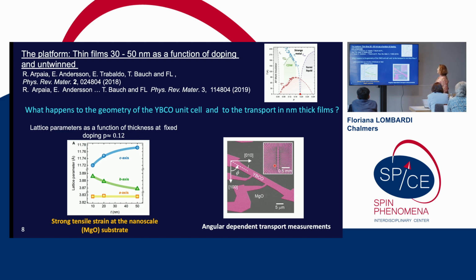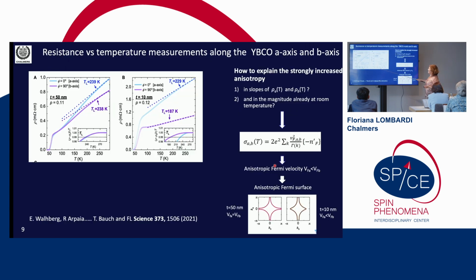Then you take these films and you make an angular dependence. So you can pattern Hall bars or nanowires as a function of the angle. And you see how the properties are changed. And this is quite surprising. This is at underdoped films, where you have depression of the superconductivity because there is competition with charge density wave. And you see the resistive transition along A and B, and they look pretty much the same because the chains are quite disordered at this doping, and they contribute not so much to the transport. So you have that the slope of this resistive transition along A and B are the same, and the deviation from linearity, so where the strange metal breaks down, the temperature is almost the same.